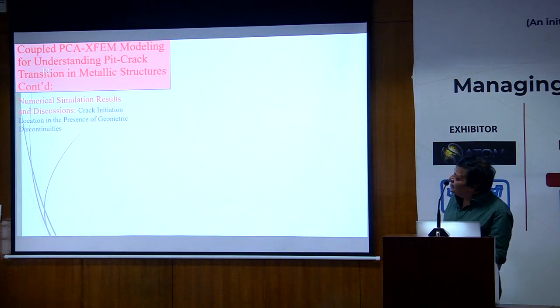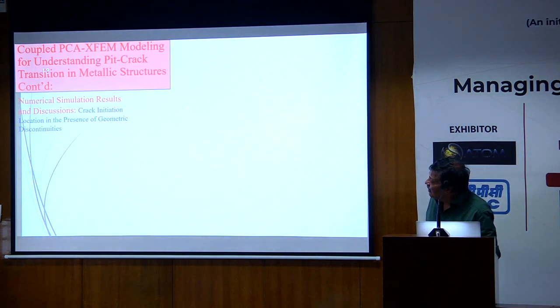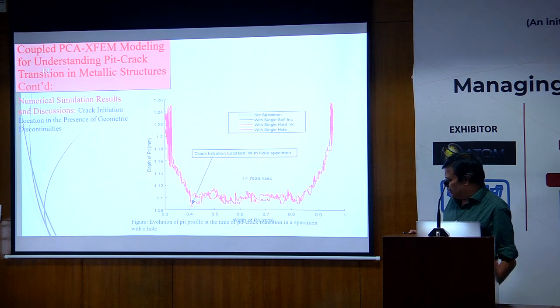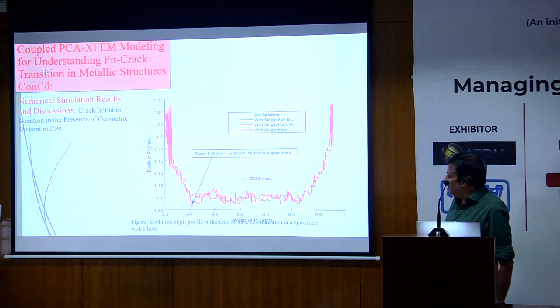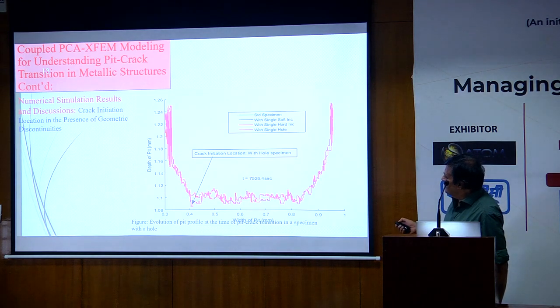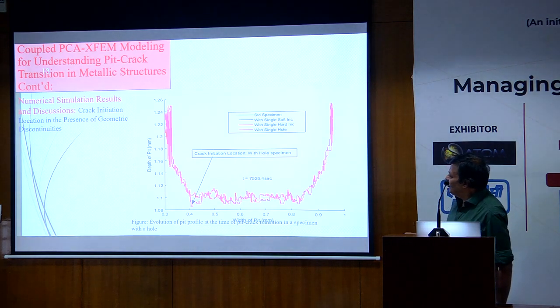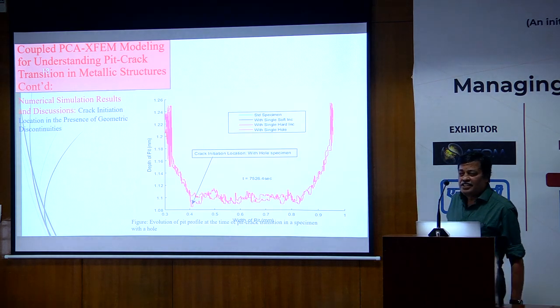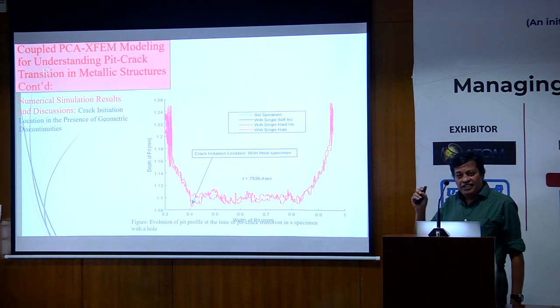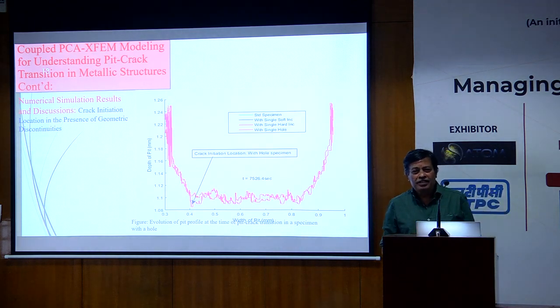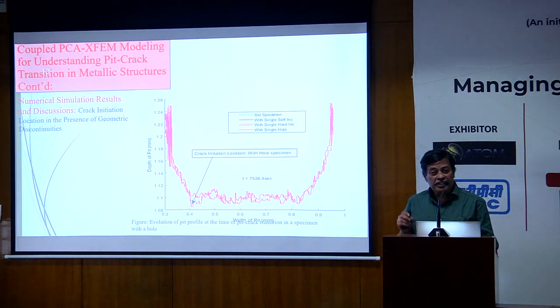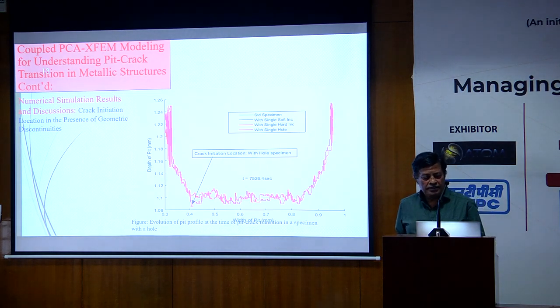So next, this is how the whole pit profile goes when there is a standard specimen, when there is a soft inclusion, a hard inclusion, and with a hole, it increases much higher than other places. So this is very critical: pitting plays a very important role and has to be taken into consideration when you have discontinuities in your samples.